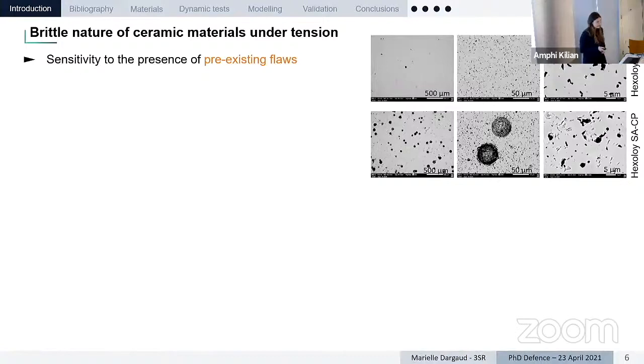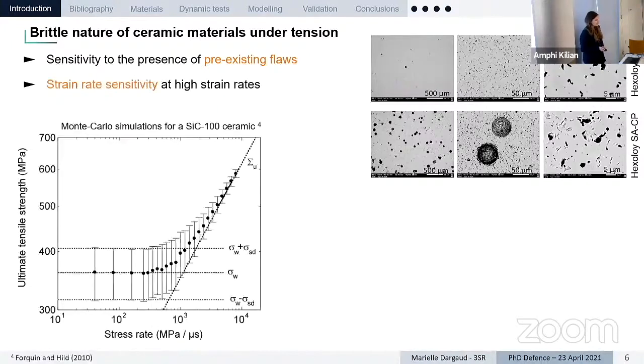So here you have images of material presenting porosity in the microstructure, which are the main defects. And this type of material, because they are brittle, they present a high strain rate sensitivity in their behavior. So here you have Monte Carlo simulations, which showed that the expected strength of a ceramic material, silicon carbide, is expected to change according to the stress rate level. And at high stress rates, we actually reach an improvement, an increase of this strength.